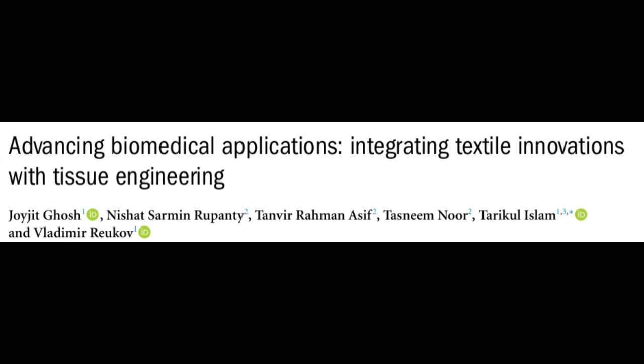And the materials are getting even more advanced. Absolutely. The sources mention integrating cutting-edge materials. For example, MXene, a type of 2D nanomaterial, when added to nanofibers, shows enhanced interaction with specific cell types like bone marrow stem cells. And for bone repair needing serious strength, they're even exploring biodegradable metals, like magnesium alloys. Biodegradable metals. Yeah. The insight is that these metals provide robust initial support and then gradually dissolve, and the magnesium ions released can actually stimulate bone cells.